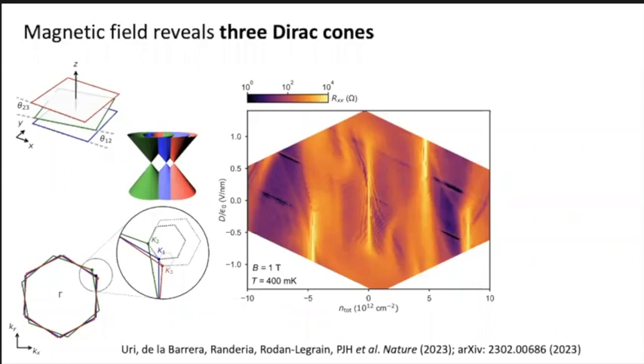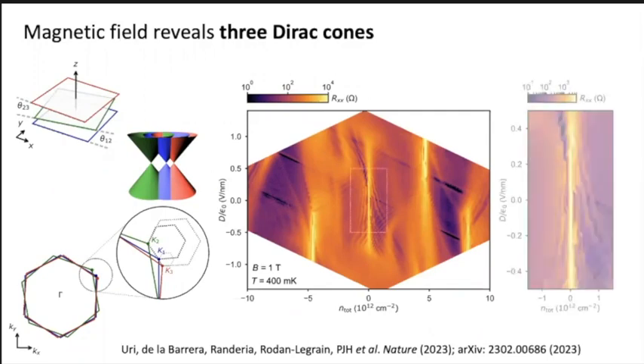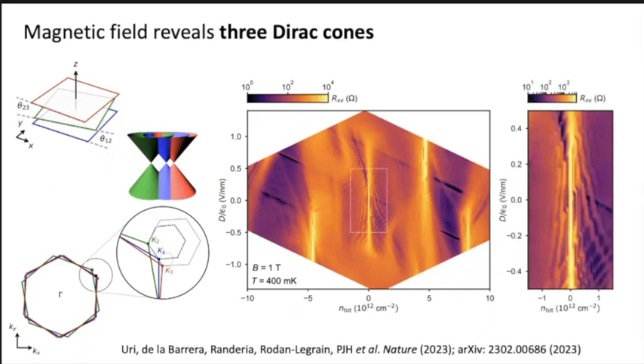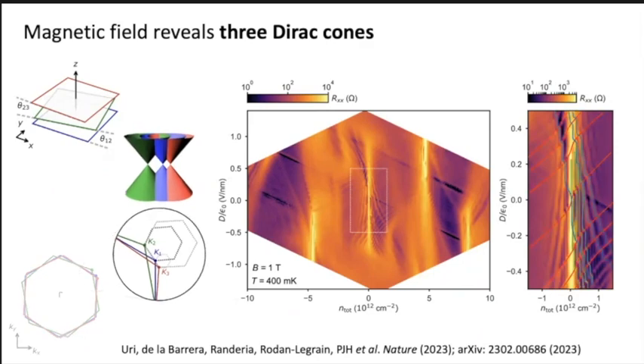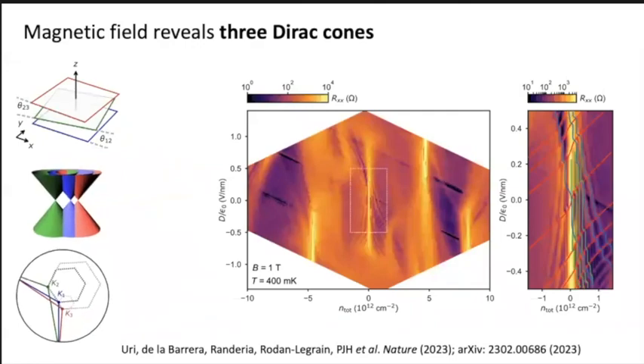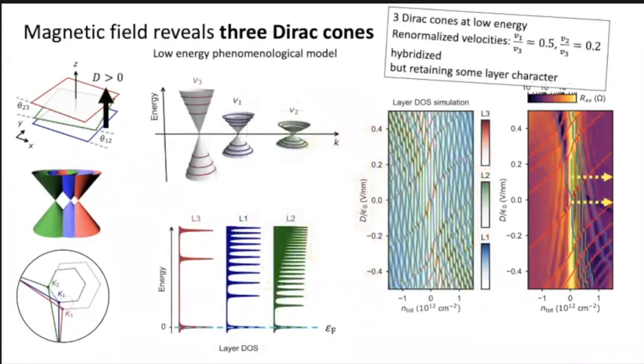But their Fermi velocities are strongly renormalized by the interaction between adjacent Dirac cones, by the tunneling between the electrons in adjacent layers, even if you're not at the magic angle condition. You can zoom in here and see there's a lot of structure. In particular, you have three sets of Landau levels which come from each of these three Dirac cones. You can do an analysis of all of this and get the normalized Fermi velocities. You don't get all three Fermi velocities, but you get the ratios of Fermi velocity 1 to 3 and 2 to 3. And as you can see, they're strongly renormalized.